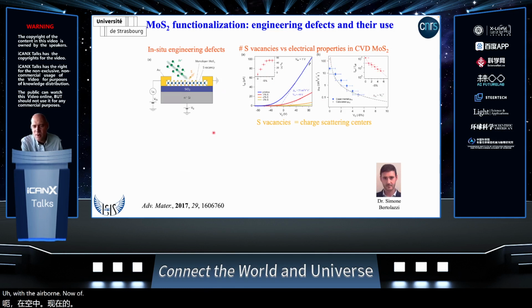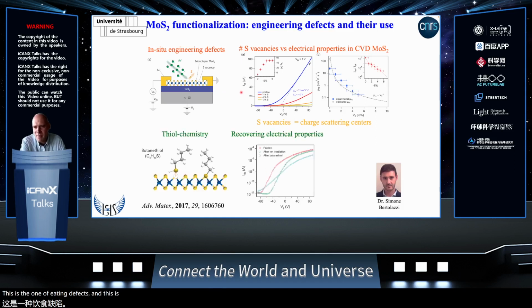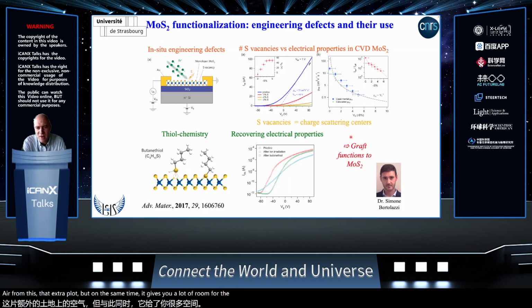Now, of course, there is always a way to solve problems, and this is the one of healing defects. Defects can be healed by, for example, here having a thiolated molecule interacting with MoS2 in order to fill the vacancy that was previously created. Now, this is very interesting because, first of all, you can recover the electrical characteristics, as you can see from this electrical plot. But at the same time, it gives you a lot of room for the grafting of different types of molecules to the basal plane of the disulfide.